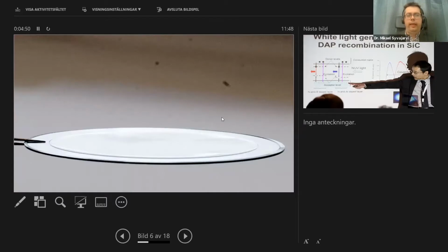But just to complete the story of my PhD, here we have a small wafer with a silicon carbide thin film on it, or for silicon carbide it was a thick film. So that was a good achievement in the growth. But it turned out that this layer was not suitable for the power devices because it was not pure enough. So it was not possible to use this for its intended purpose at that time. So the highlight of my PhD thesis was a process for making material which was not useful. So that was 1999.